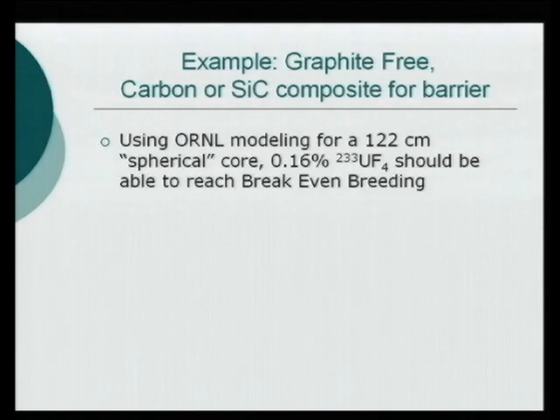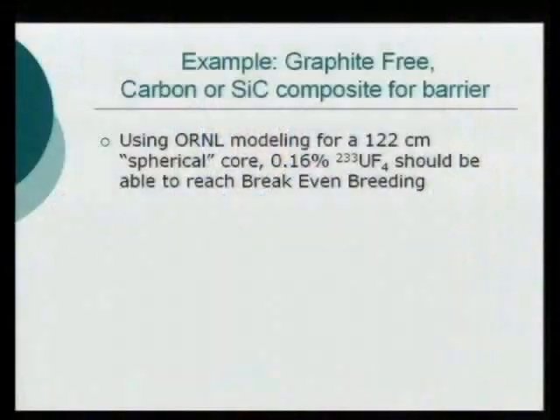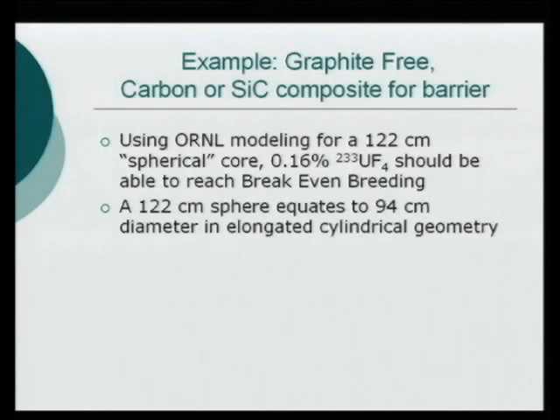Just to show some numbers, and I can back these up, I do a lot of data mining, okay? Taking studies that were done by Oak Ridge or the French or the Russians, or the Japanese, Czechs, et cetera. In their studies, Oak Ridge studies for a 122 centimeter diameter sphere with 0.16% fissile concentration, that should be able to reach break even long term. If we extend that to long cylinder geometry, that shrinks down a bit to just under a meter in diameter.